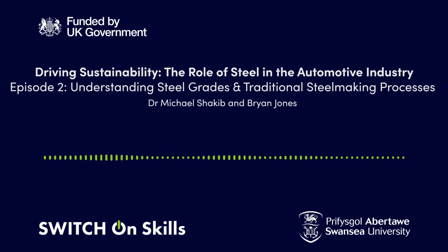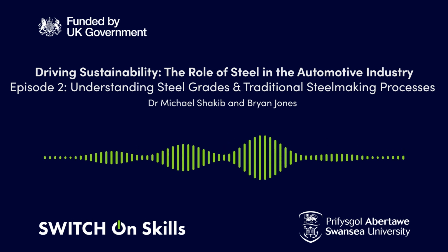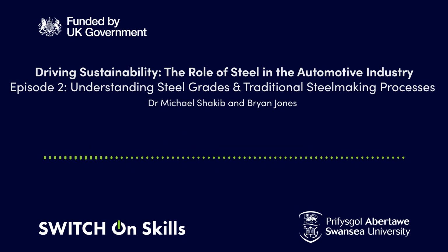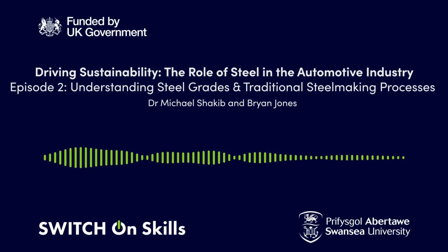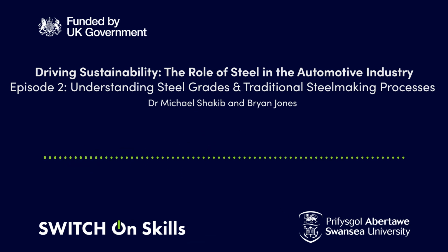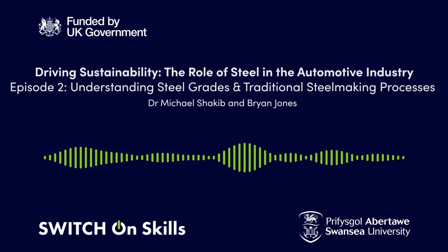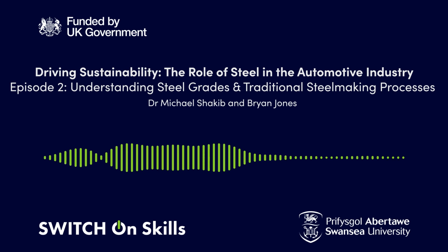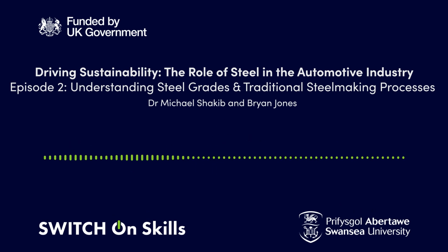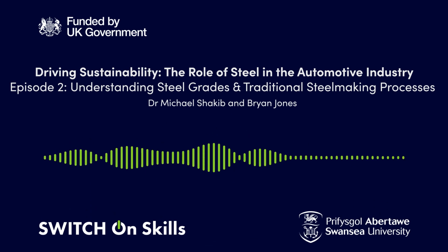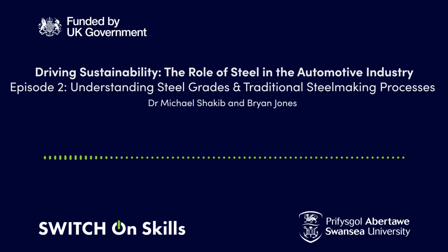You then melt the steel, and you add things such as flux, which aids in removal of some of the impurities that are present. So you get a slag film developed on the outer surface of the molten steel in the furnace. You also use carbon and oxygen injection, which again is beneficial in removing impurities.